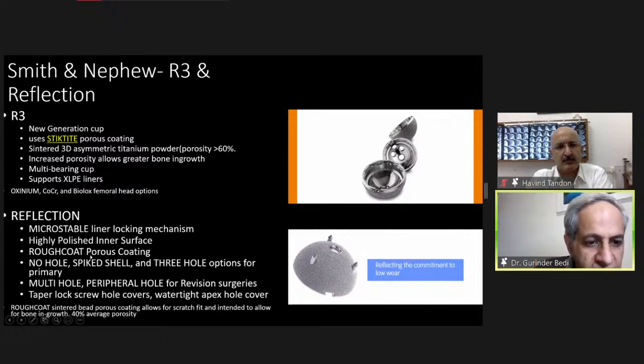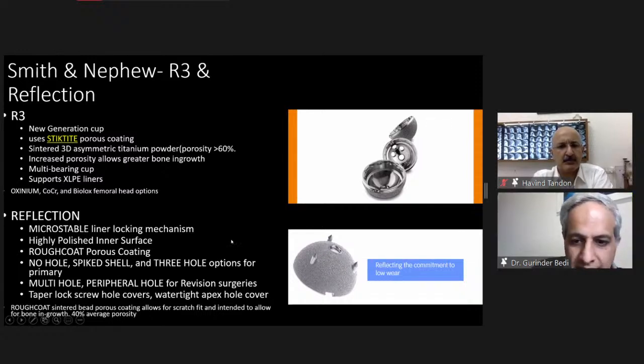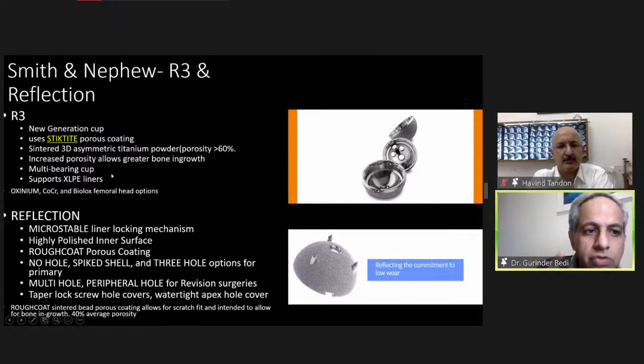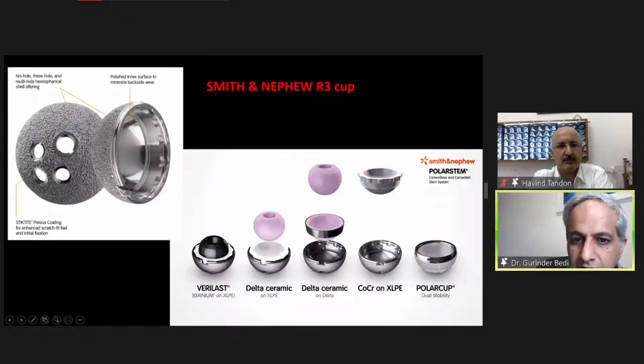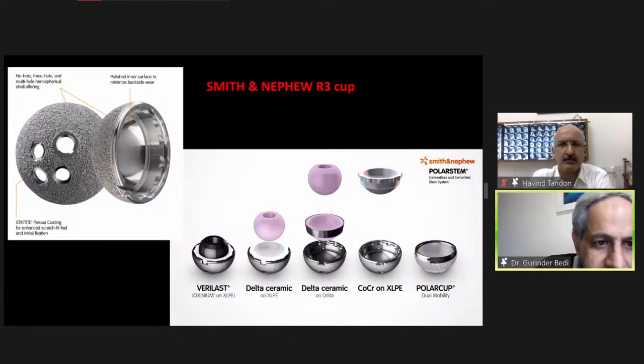Reflection is the one which is just before this. This had what's called a rough coat, porous coating. And again, different options are available. This has the spikes and all. Smith & Nephew is really now talking about R3 because the results of the R3 are actually coming out better. What you have inside is a very polished surface, which is cobalt chrome. And the outside of that is the STIKTITE technology, which is basically titanium, but it's sintered titanium, not a plasma sprayed titanium. So the coating is there, but it's sintered. And these are the things which are available.